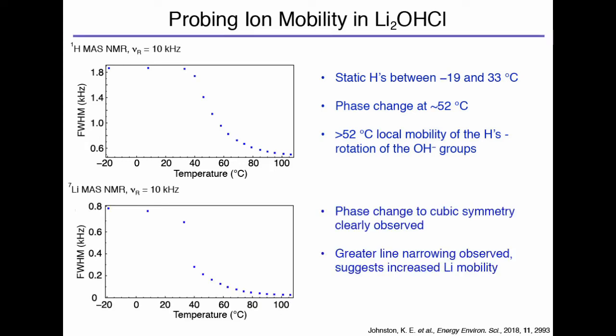We can do exactly the same for the lithium. And what we see in this case is, you can clearly identify the phase transition, which is occurring here. But what we see is a much greater line narrowing. So the line gets much, much more narrow relative to the proton. And what that seems to suggest is you've got a different type of mobility occurring in the lithium relative to